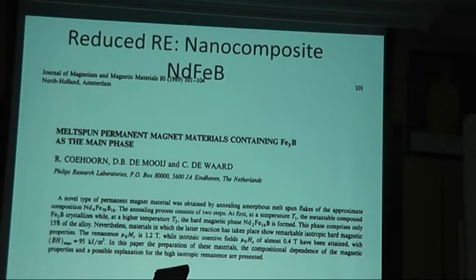So they try to make a composite with iron boron and NdFeB. They reduce the amount of rare earths. For stoichiometric, Nd is around 12%, but they reduce it down to 4% of NdFeB. In this material the dominant material is iron boron, so the remanence increases up to 1.2 Tesla. Normally single phase NdFeB can only reach 0.8 Tesla. So they enhance the remanence.